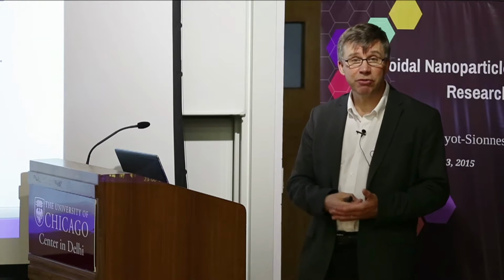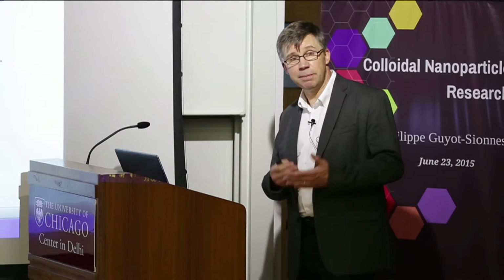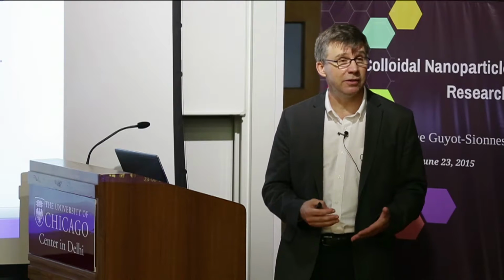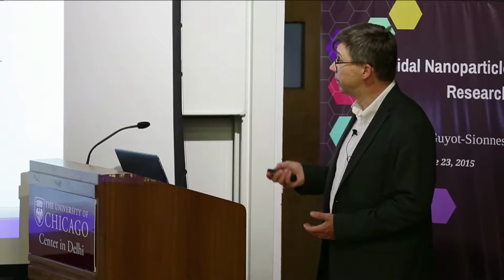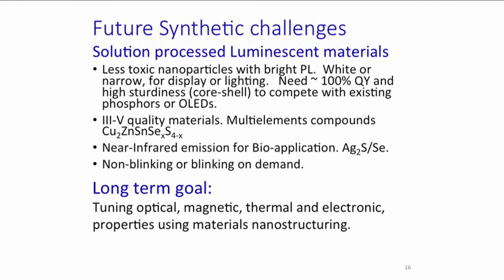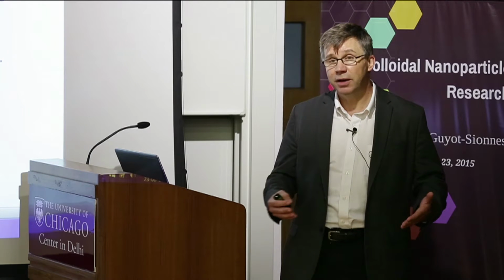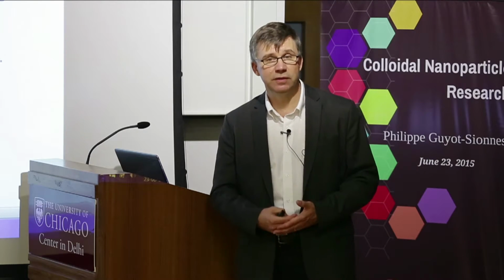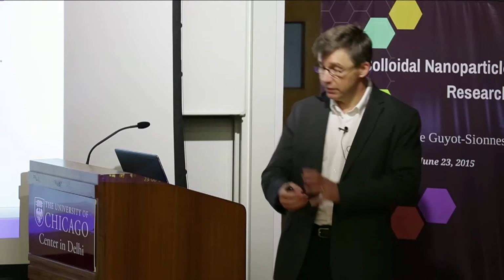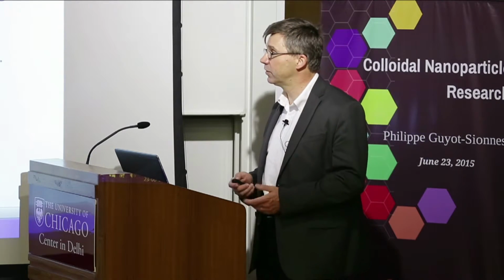There is a synthetic challenge to make III-V materials of good quality. For example, gallium arsenide still does not exist as a nice colloid. There will be challenges to make multi-element compounds, such as, for example, CZTS, copper, zinc, tin, sulfur, or selenide. This is made out of less toxic, widely abundant materials. And in principle, this material should be tunable through the visible spectrum to lead to luminescent nanoparticles, but nobody's done it yet. Why? Probably because composition, surface, size distribution, and the uniformity of the composition are not controlled yet.